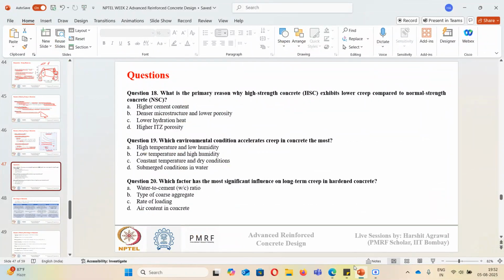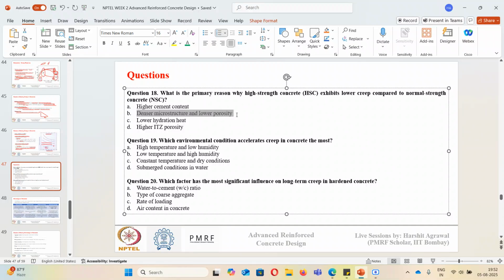Okay, so yes, for question number 18, the answer is B. The primary reason why high strength concrete exhibits lower creep than normal strength concrete is the dense microstructure. So we have a stronger cement paste matrix in high strength concrete, which is subjected to less creep, and lower porosity. Since there is lower porosity, there is lower moisture loss from concrete, and there is weaker crack propagation over a sustained loading inside concrete, which contributes to lower creep.